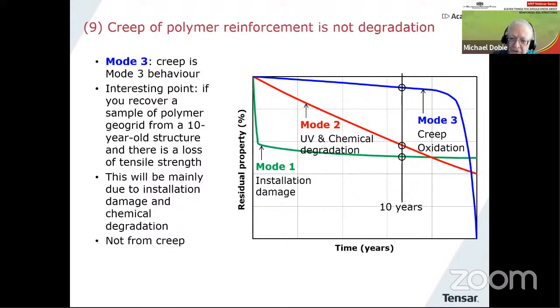And that reduction in strength is going to come principally from the initial installation damage, combined maybe with chemical effects or exposure, if it's an exposed piece of geogrid, UV light, but not from creep, not to any significant extent, because creep is not degradation. And I hope that this little discussion gets that point across. But we still have to take into account long-term behavior in terms of a creep reduction factor.